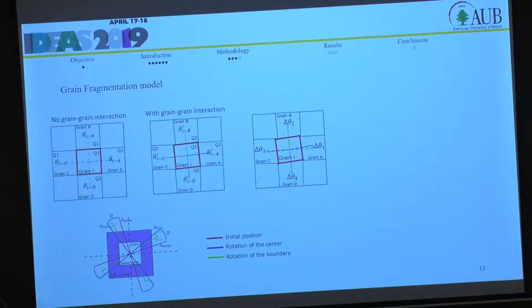So how will this effect be implemented? First of all, we take 2 calculation steps. The criterion for grain fragmentation to occur is having a misorientation angle between the center of the grain and the boundary of the grain. So when this misorientation angle exceeds a certain threshold value, the grain will split into 4 new grains, and these new grains have the ability also to split more and more. So how is this misorientation angle calculated?